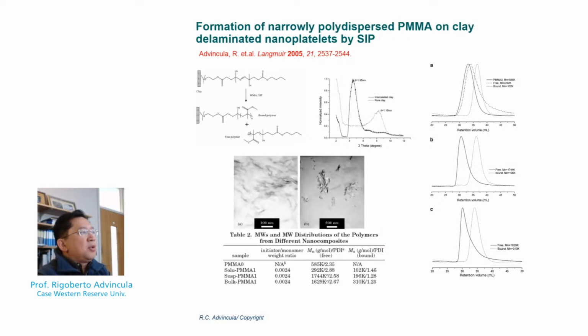One of the ways that we prove this can be done on a clay is that we are able to produce very monodispersed systems, let's say with this particular design. So in this case, we have a monocationic design which we inserted in clay. The difference is that in this particular experiment with PMMA, we actually achieved low polydispersity, or a good polydispersity, with the different reaction conditions that we did with PMMA on clay. So to our surprise, these are very good systems that confine polymerization, resulting in low polydispersities.